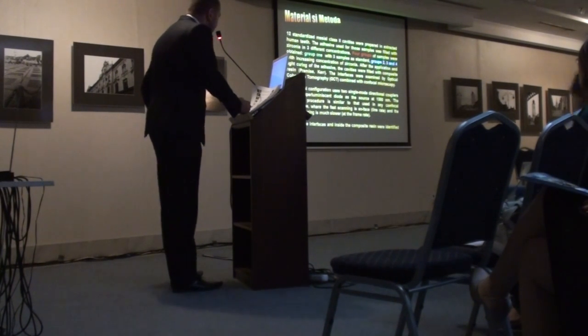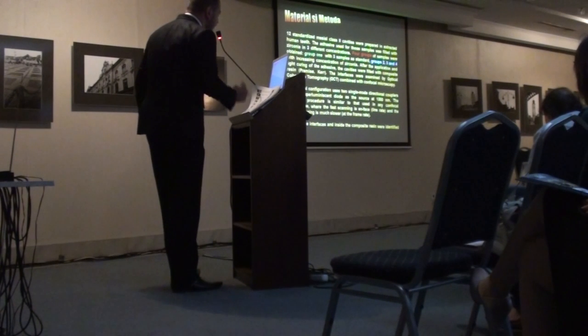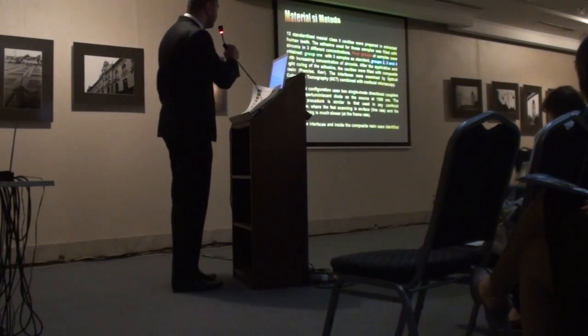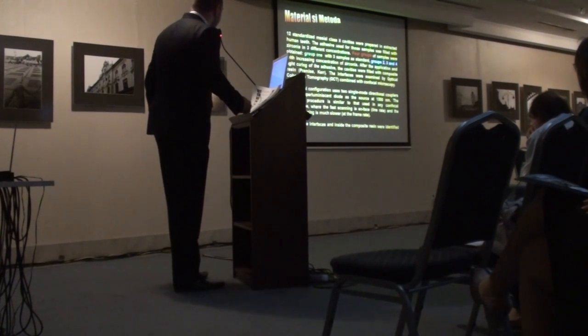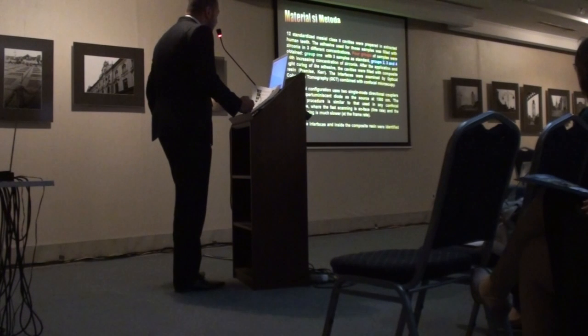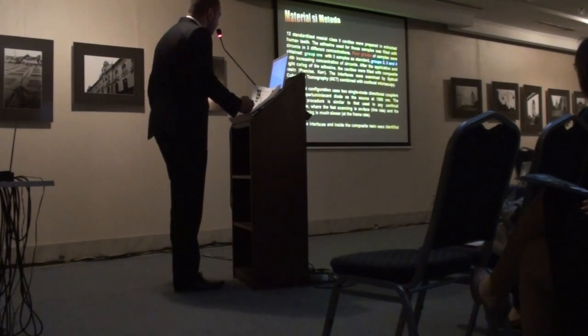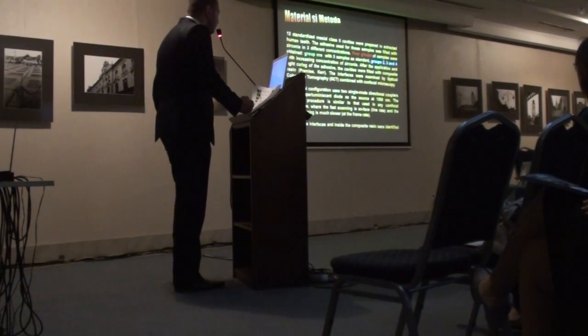Materials and methods. First, standardized mesial class 2 cavities were prepared in extracted human teeth. The adhesive used for those samples was filled with zirconia in 3 different concentrations. 4 groups of samples were obtained. Group 1 with 3 samples as standard, group 2, 3 and 4 with increasing concentration of zirconia. After the application and light curing of the adhesive, the cavities were filled with composite resin.